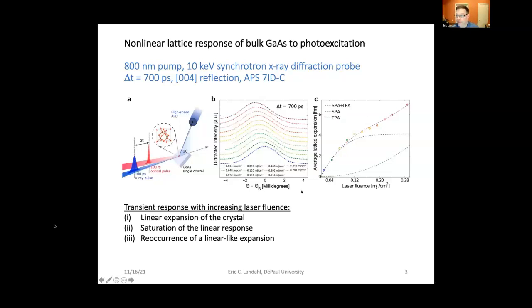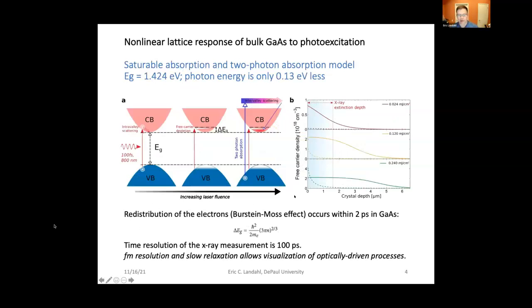That can be described by a purely optical absorption and electron model. So with increasing laser fluence going from left to right here, we first see single photon linear absorption. And then eventually, via the Burstein-Moss effect, a rearrangement, which happens probably very quickly, 2 picoseconds or less according to the literature, a depletion of free carriers in the conduction band. And that is what gives rise to the saturation effect.